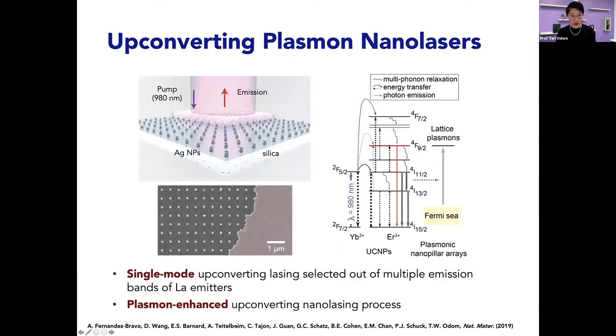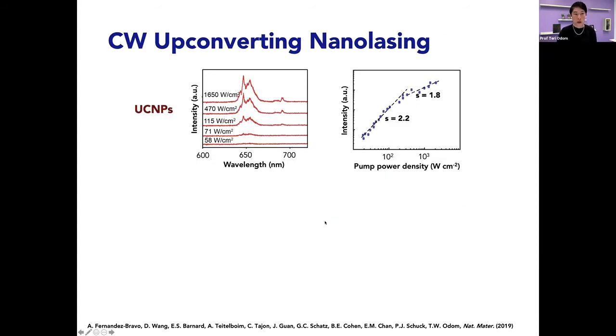And also if this can be plasmon enhanced. So if we just consider a slab of up conversion nanoparticles, you can see that there is more or less uniform increase for these different electronic transitions as a function of pump power. And if we look at this on a log plot, you can see that the slope is about 2. So that's the 2 photon process involved, and it reduces at very high pump powers because of saturation effects.